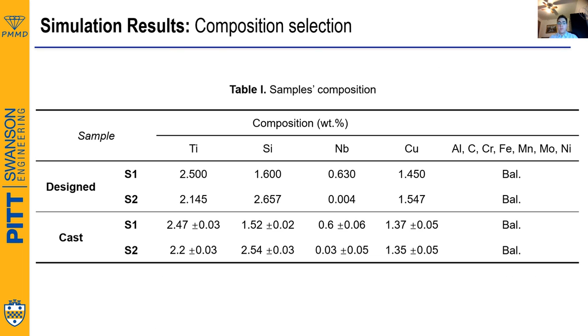Now, after screening thousands of compositions, here in the table you can see the best two candidates, and we are listing here for you the most relevant element composition of both samples. The design composition, as you can see in the first two rows, is the retrieved values from the ICME model, while the cast values on the last two rows are coming from the EDS data from the cast ingots. Both samples you can see are very similar in their composition.